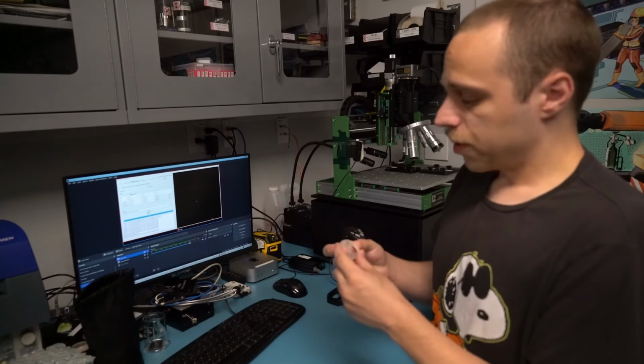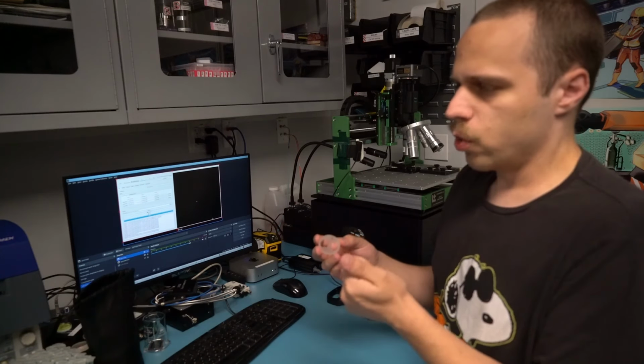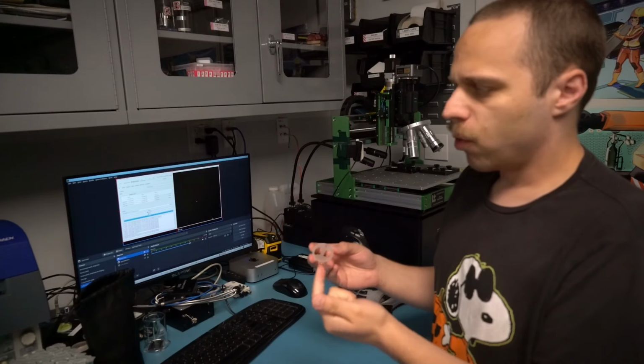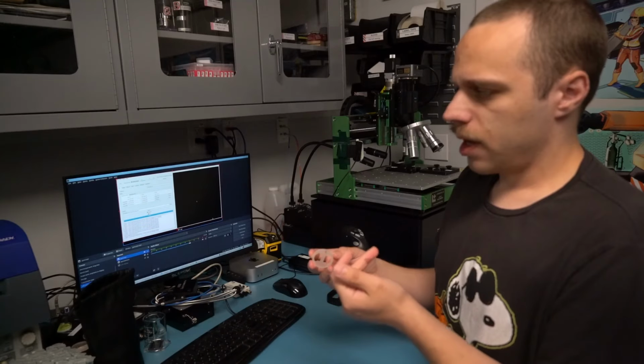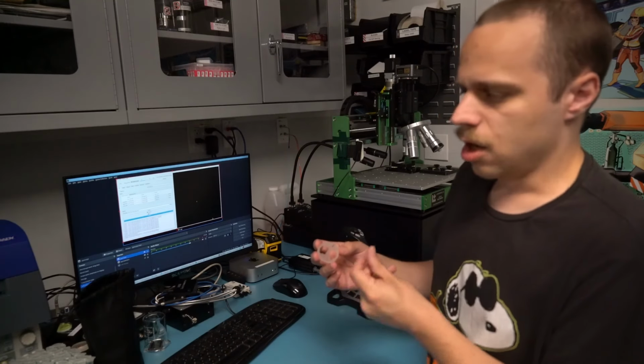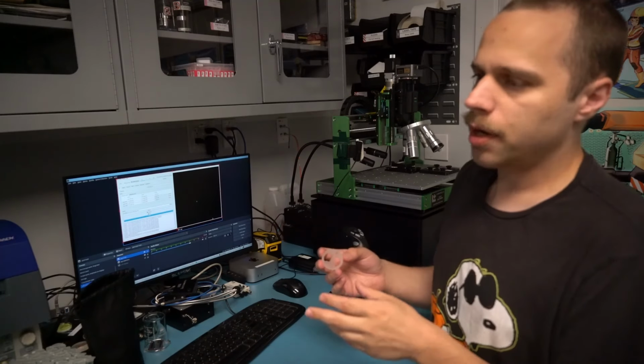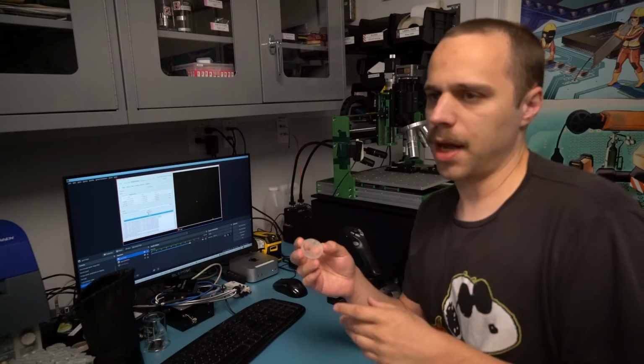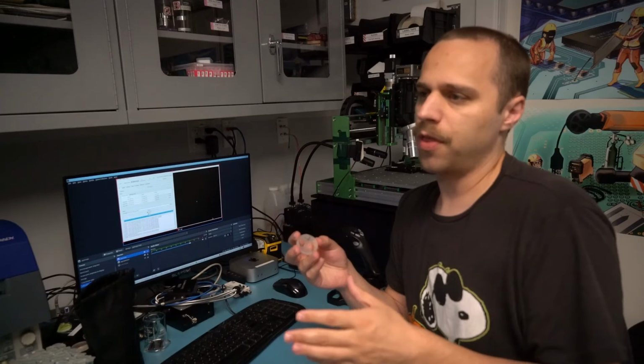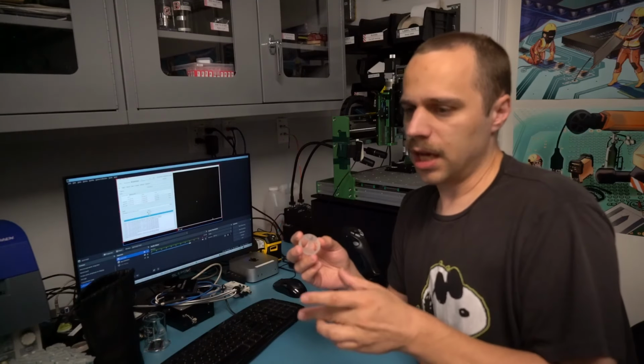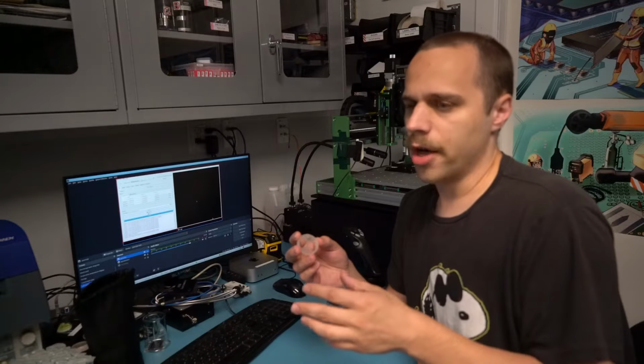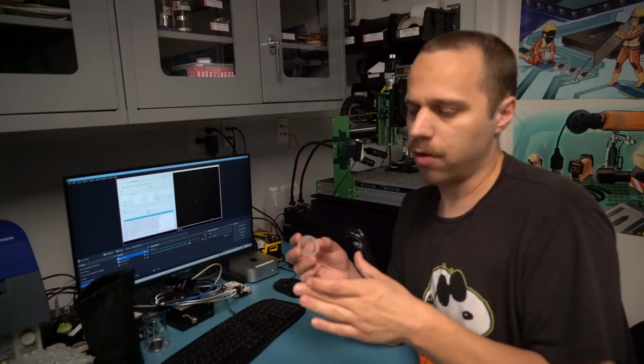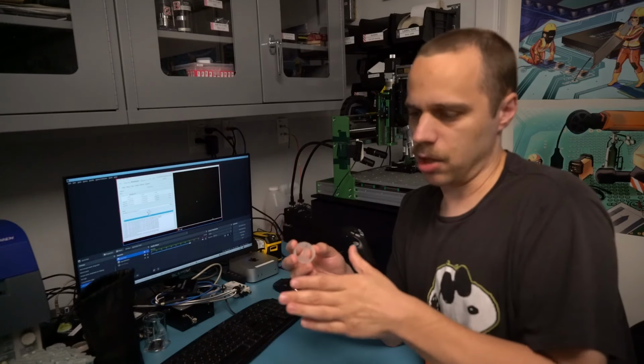So here we are after a bunch more polishing. I went through P180, P400, P800, P1200, and then 2500. Probably went to 2500 a little too soon. I ended up spending a couple of hours there, but silicon is really brittle, and especially with this sort of system, it is very easy to crack it and cause fairly large amounts of damage that you have to polish quite a bit into to remove.